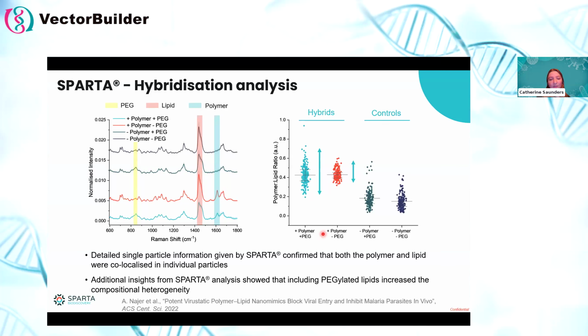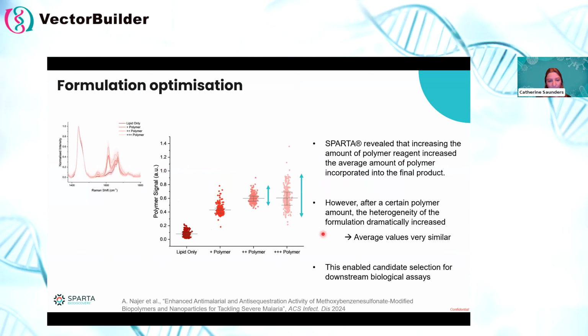But in the next stage of this study, this really came more into play. As a follow-up, the same researchers were interested specifically in targeting severe malaria. What they were doing with this was some formulation optimization, increasing the relative amount of polymer in these formulations. We can do a similar analysis and compare the amount of polymer signal for each of these formulations.